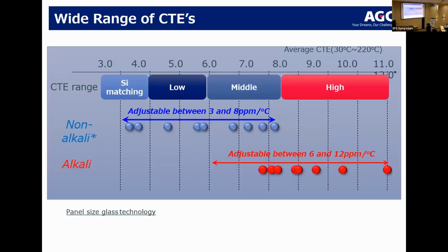So CTE is one of the most important parts of a package, and there's a variety of CTEs available. But you see there's a transition point at about 7, 6. So you go from a non-alkali material to an alkali material. Remember, any alkali that's in the glass attenuates the electrical signal. So you cannot have alkali materials in it.